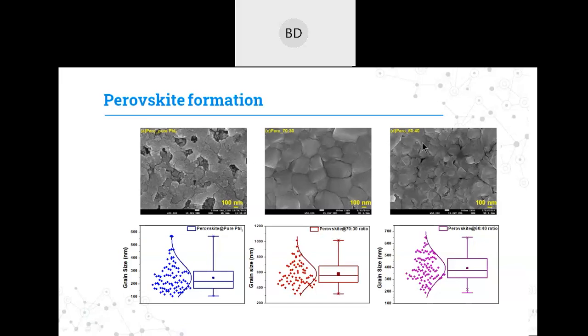If you further increase the concentration of the lead nitrate, then it starts deteriorating the morphology again. It's because the more the concentration of lead nitrate, it starts forming chunks in the perovskite structure. So the 70-30 ratio is the optimized ratio for this process, where we can get a very good quality perovskite film, a very compact film with a very small number of pinholes.